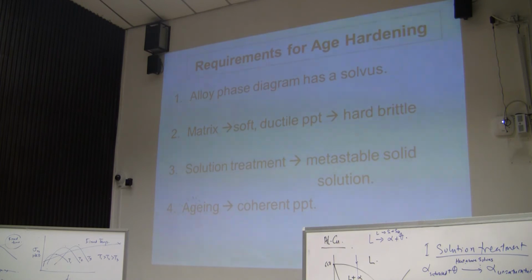If it is solution treated, it is a supersaturated solid solution, very soft, and you can deform it very easily. So rivets need to be deformed. After that, you have to go through aging to strengthen it.